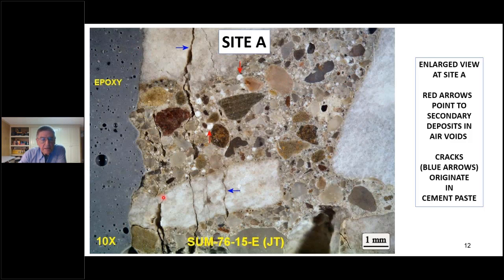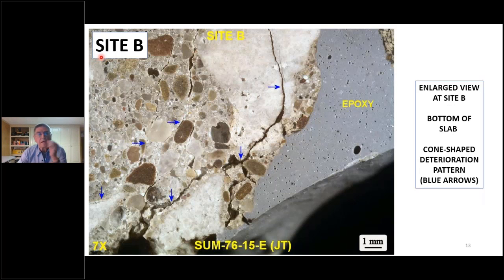But in all of this area, you're seeing the compromising of the air void system. And now you have the cementitious phase acting like it's non-air entrained. All the cracks that you're seeing here are originating in the cement paste phase, which is acting like it's not air entrained. And the cracks then pass through the aggregate particles. And you'll notice that the crack pattern here is totally different than it is with D-cracking. With D-cracking, the aggregate itself is experiencing the problem. Here, these are durable aggregates, and you're simply propagating the cracks originating in the cement paste through the aggregate particles. And then eventually, after enough cycling, this concrete will completely lose its ability to provide any kind of support. The same thing is present at the bottom. This is site B, as I mentioned before.